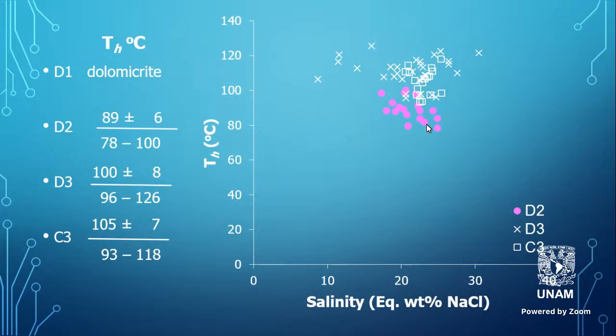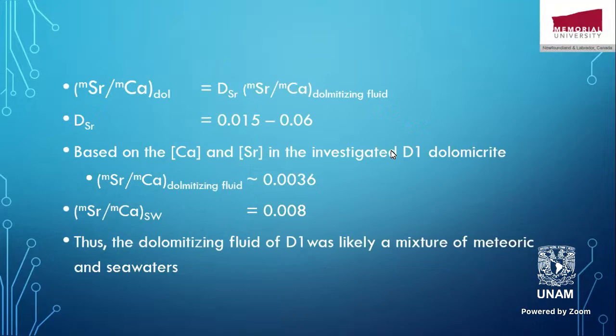From the melting points, one can build up estimates of the salinity, and when we plot the homogenization temperature against the salinity, we can see the generations of dolomites and whether they overlap or not. You can see that there is some overlap, particularly between C3 and D3, because they were the latest generations of cements. But D2 has a lower homogenization temperature. If we look at the salinity, all of them overlap. This may suggest that they originated from almost the same type of fluid, whose composition evolved through circulation in the basin.